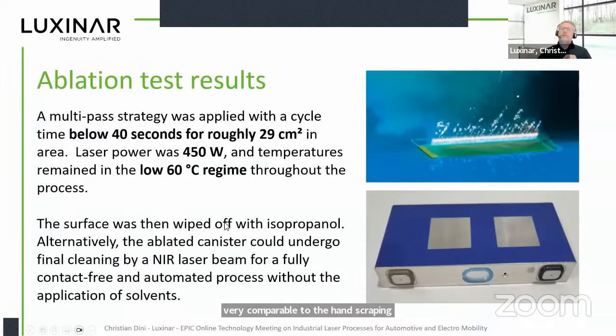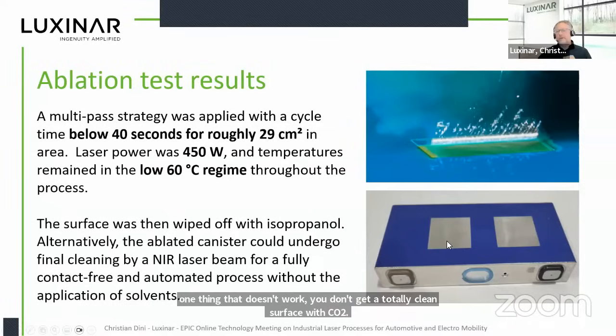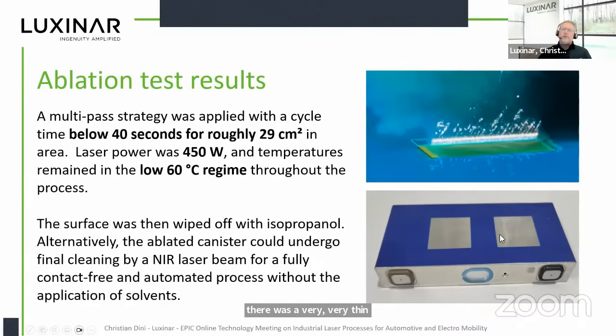And the one thing that doesn't work, you don't get a totally clean surface with CO2. There was a very, very thin sticky residue left, but that was easily wiped off with a little bit of isopropanol, so a very mild solvent compared to what they typically use. And that could be also fully automated. So this whole thing, from removing the wrap to removing the residue, could be an automated process.